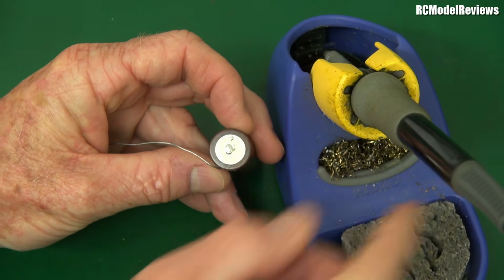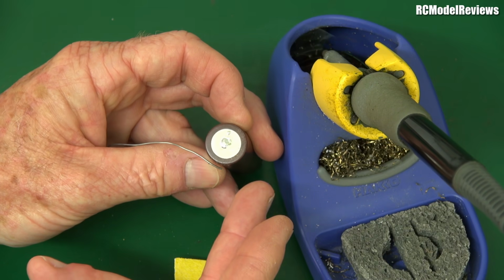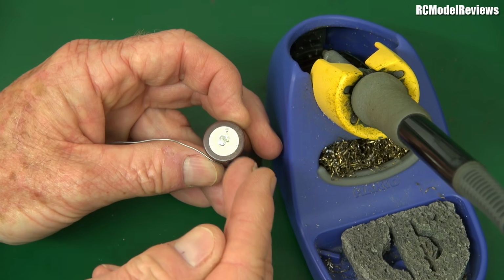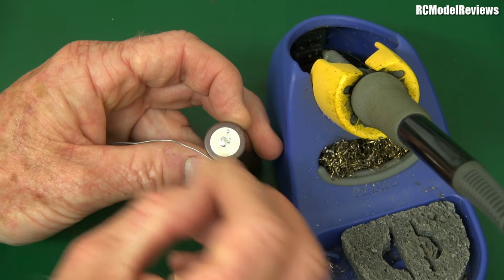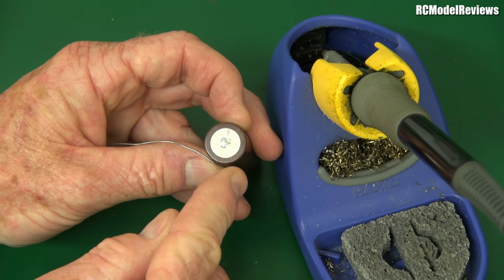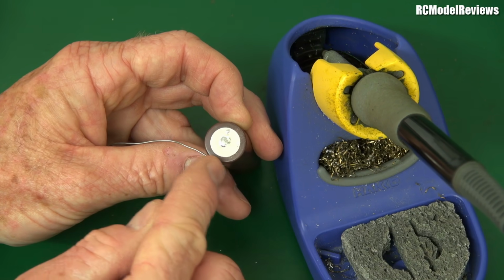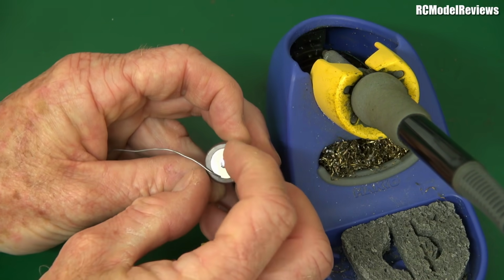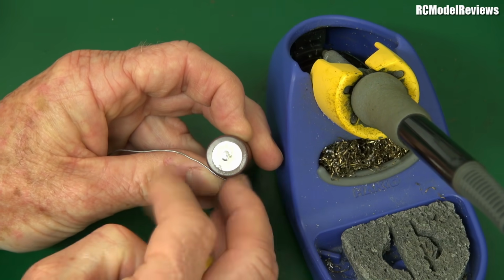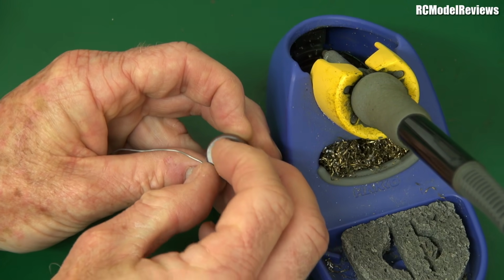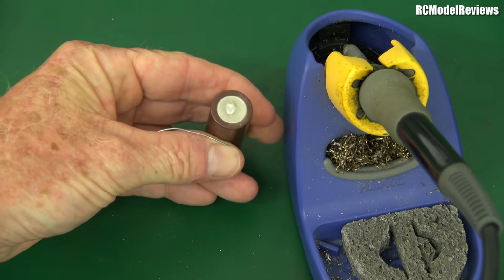See that? So I had solder on the tip of the iron and I fed solder in as I put the iron onto the bottom of the battery. Then I gave it a bit of a swirl around with the tip of the iron just to make sure. Instantly alloyed. Now there's a little bit here which might not be. Yeah, that wasn't. See, there's a little tiny piece there that was just sitting on the top of this. The rest is totally stuck to the battery.